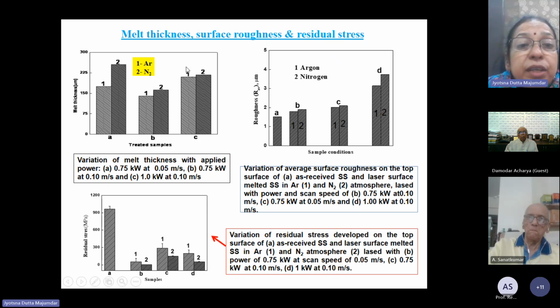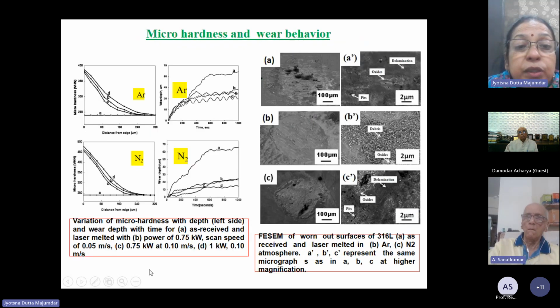So these are the different effects of the environment on the melt zone thickness for different samples, combinations of power and scan speed. As you go on increasing power, you see that depth of melting increases. As you go on increasing scan speed, depth of melting decreases. So these are very common observations. But what is interesting is that there is significant improvement in hardness both in argon as well as nitrogen environment. Nitride formation is there, but it was not really so high, so we get a little higher hardness when we do melting in nitrogen environment. As a result there is also an increase in wear resistance. There is a significant decrease in wear rate for both cases,